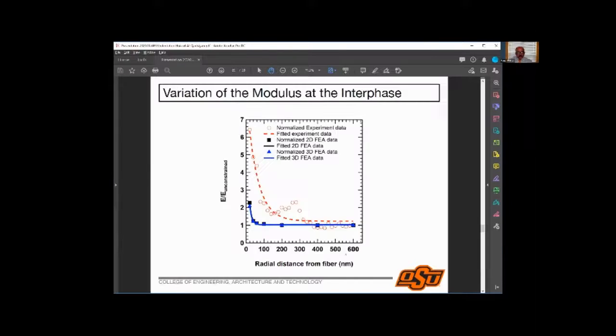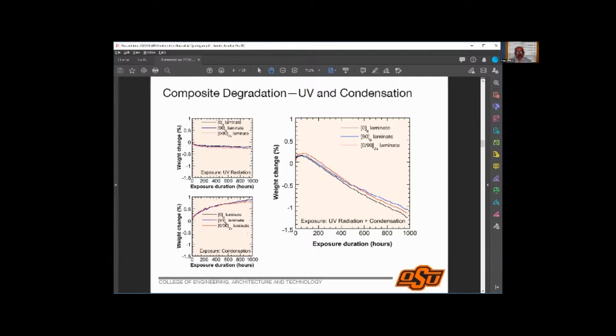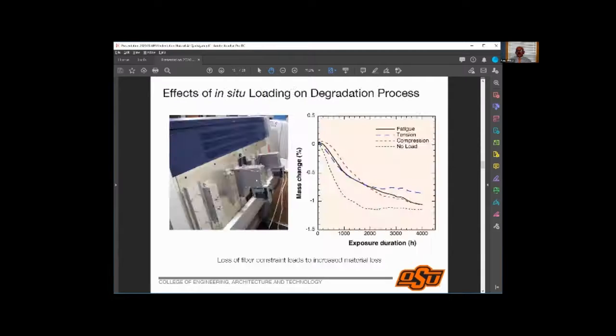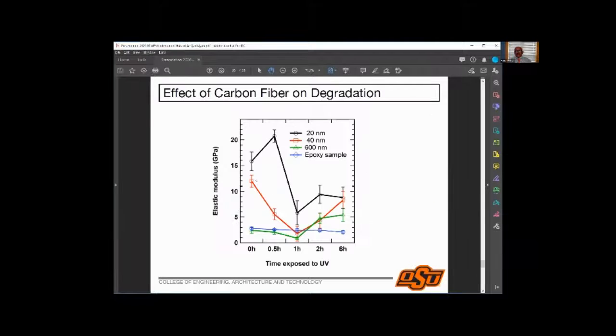To give you an example, when we first started out, these experiments were very long duration experiments. These are 1,000-hour experiments. So if you're dealing with a bulk composite laminate, then with UV exposure, you have to carry out very long duration exposure before you start seeing changes in the material properties, right? Here we start seeing changes very fast, because these indentation experiments are probing only the top 10, 20, 30 nanometers of the material, which almost immediately gets exposed. We start picking up these changes not only within 6 hours, but within 30 minutes, because UV penetration in the top 1 micron is almost instantaneous, right?